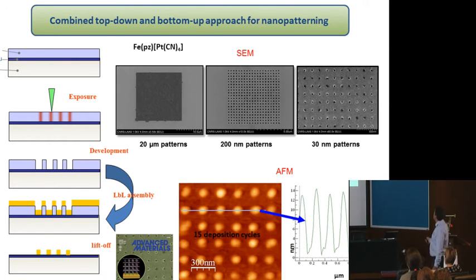So it's possible to obtain different sizes and also different geometries. Here are just AFM measurements. Here we can follow: these dots correspond to 15 deposition cycles. Normally the theoretical value for one cycle is 0.7 nanometers per layer. So if you multiply 15 by 0.7, we found about 12 nanometers. So you have a very nice deposition. It's like epitaxial growth, in fact, of the films.